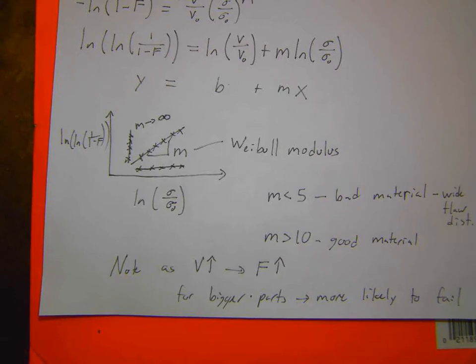when you have, say, bulk alumina, so large scale, you have some low average strength, less than a gigapascal. As you reduce that volume, you get this statistical increase. So you're statistically getting stronger and stronger up until a point where you reach the theoretical yield strength of a material. So that's the strength at which atoms rupture. I had mentioned that, I think, sometime maybe last week. But if you make your part small enough, this point happens around 20 nanometers, you actually get to the point where your materials will be the theoretical strength of the materials statistically.